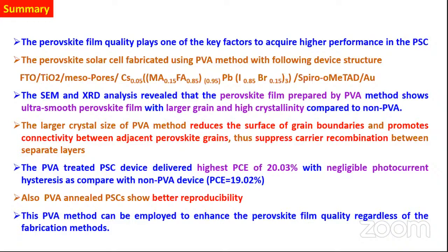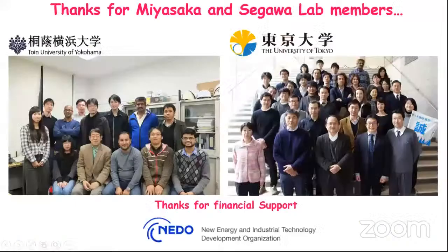From this, when decreasing the surface recombination, the efficiency is improved, from 20%, and negligible photocurrent hysteresis compared with the non-PVA method. And also this PVA method produces high reproducibility compared with the non-PVA method. And based on this, this PVA method can be applied to enhance the perovskite film quality regardless of any fabrication method.